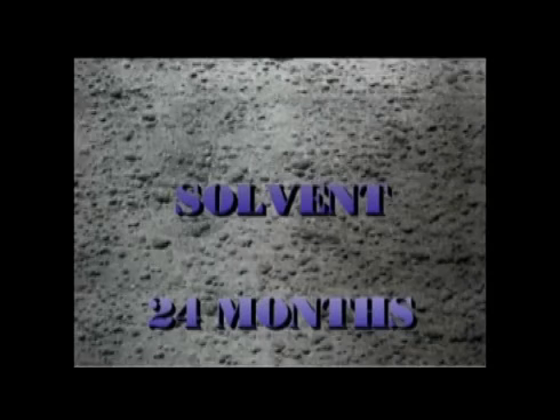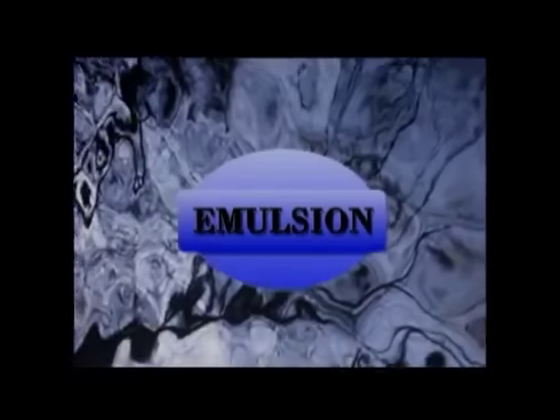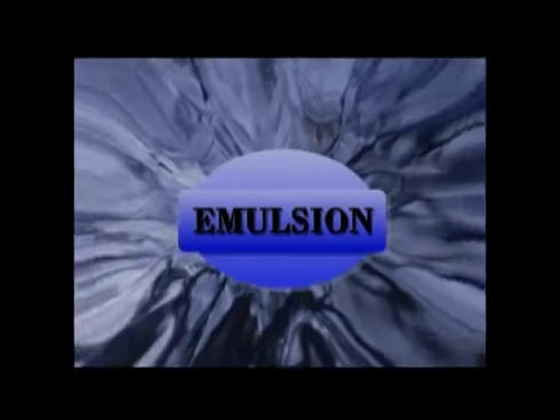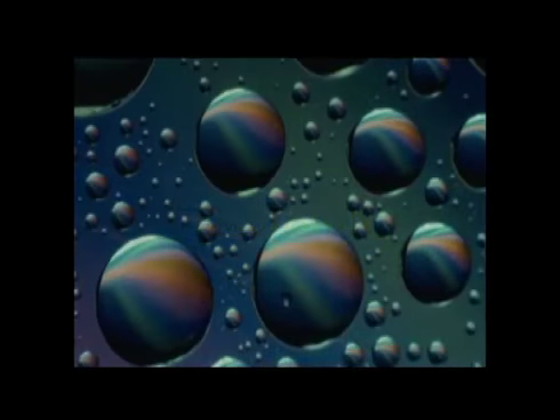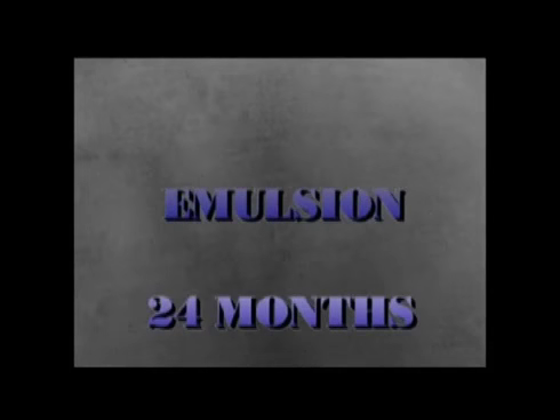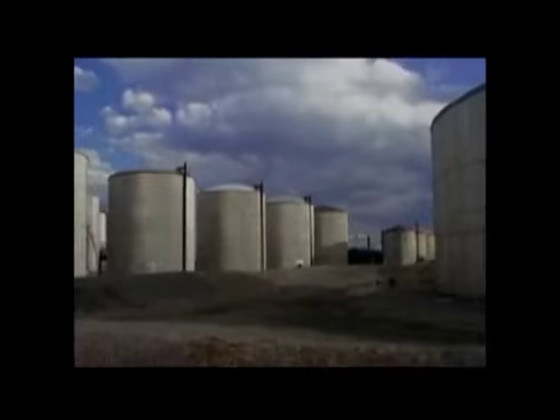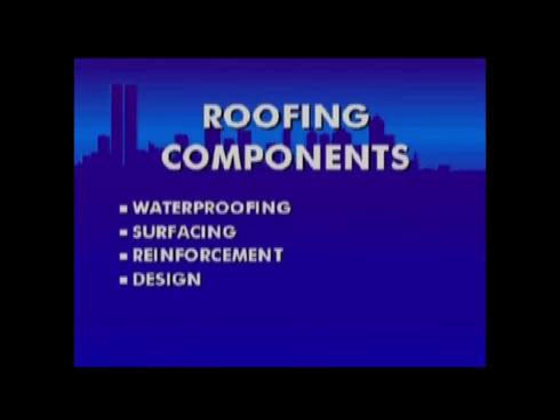At 24 months, hot asphalt and solvent-based asphalt can also carbonize and become brittle. But one form, emulsion, which is pure asphalt, liquefied in water and bentonite, has had an exceptional track record in roofing. After the water evaporates, the bentonite forms an inorganic stone barrier that protects from sun, heat, and water. Emulsion eliminates the problems with fire and toxics, and is so watertight that it's also used for reservoirs and tank linings where water is in constant contact. In looking at choosing roofing components for waterproofing, emulsion's a watertight choice.